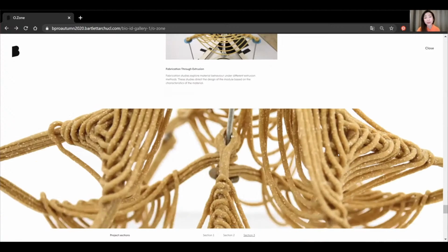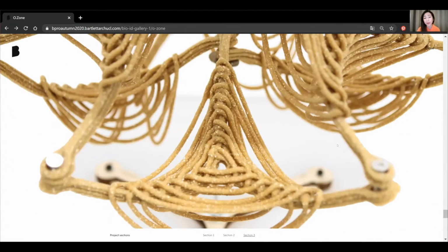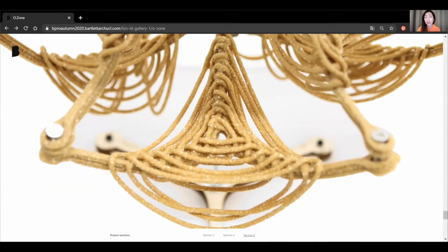And this assembled prototype shows the deformation that appears when exposed to humidity, which is also a common issue shared by all biomaterials. Although one of the mixtures has been shown to increase the elasticity of the material, the stability of the structure is still unpredictable. Hence, the environmental parameters which affect relative humidity, such as surface radiation and wind, became the fundamental drivers of our